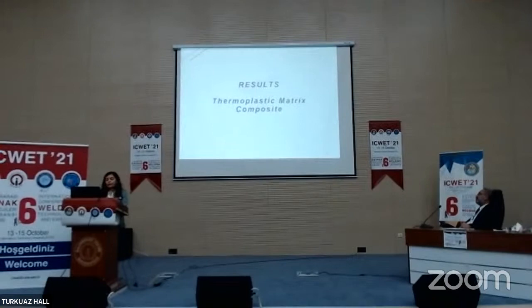Thermoplastic matrix composite panels, which are manufactured from PEEK resin and bidirectional carbon fiber, having 2 mm thickness, are treated by Nd:YAG laser. The first study is done by keeping wavelength, frequency, focus distance, and power parameters constant. Scanning speed parameter is investigated at different pulse distances. As you can see, the contact angle versus scanning speed graphic shows that the optimum speed is obtained at the blue line, which represents 100 micrometer pulse distance with 45 millimeter per second speed.